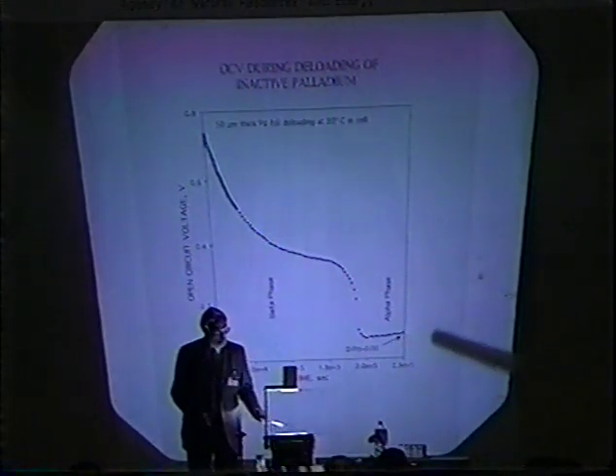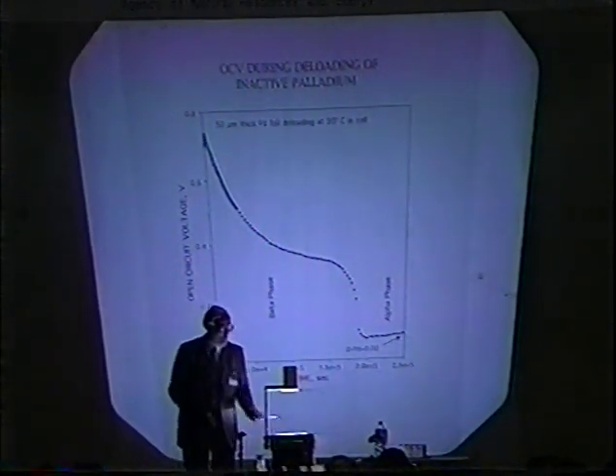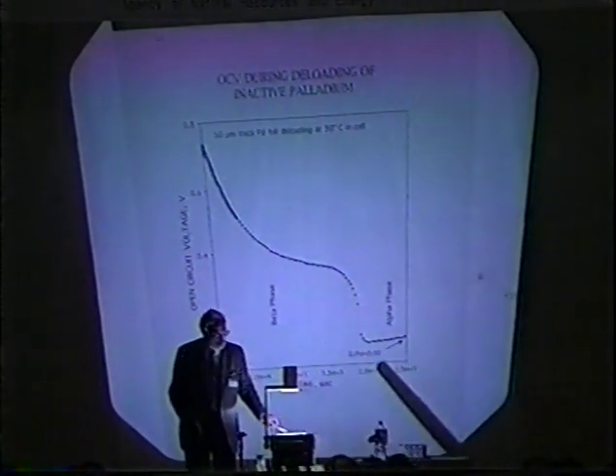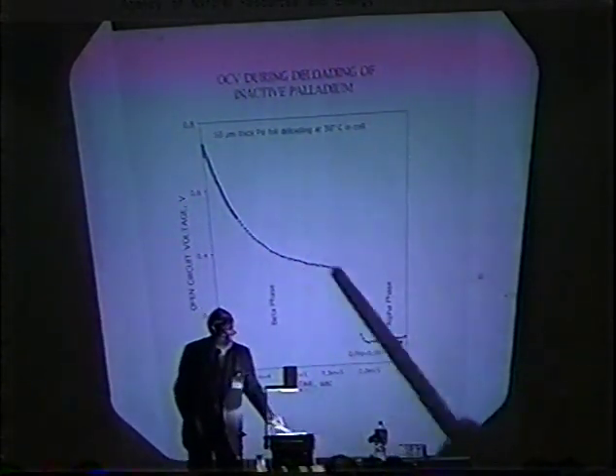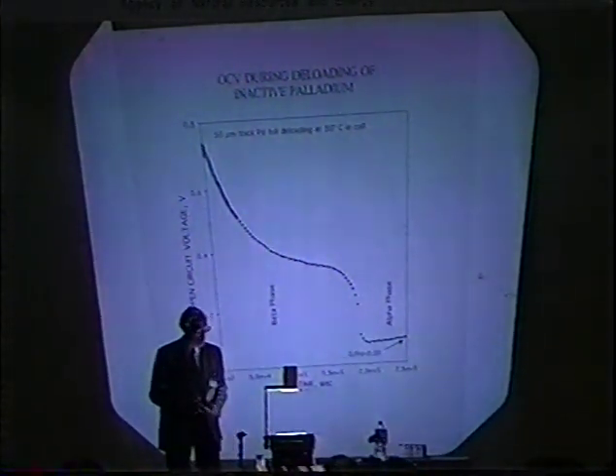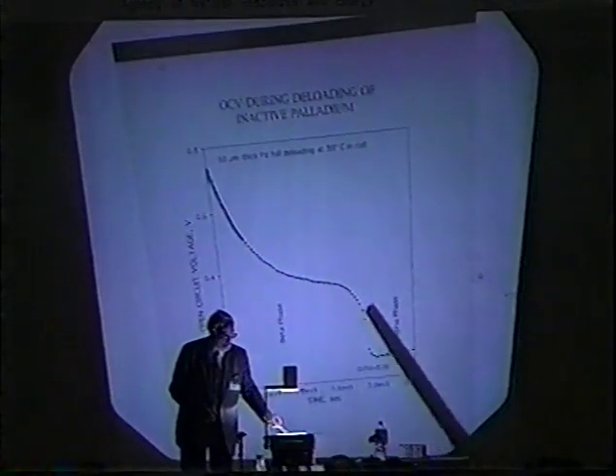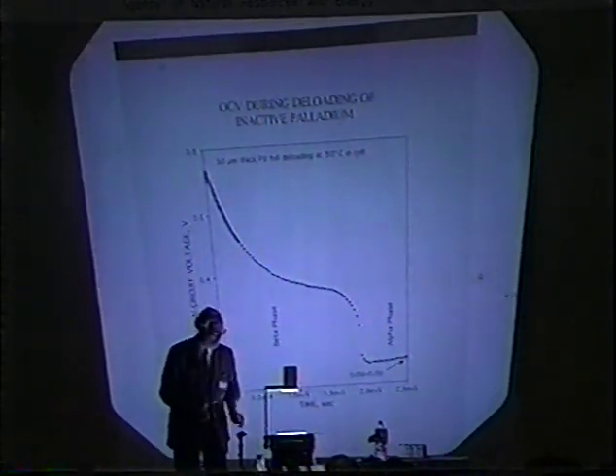This is an example of a piece of palladium that produced no excess energy. It was loaded, it went to an open circuit voltage of about 0.75. This was allowed to deload while the open circuit voltage was measured to show how it changed as the composition changed. And you can see it drop down to the alpha phase, and if it had gone long enough, it would have gone back down to zero. That's an example of a dead sample.